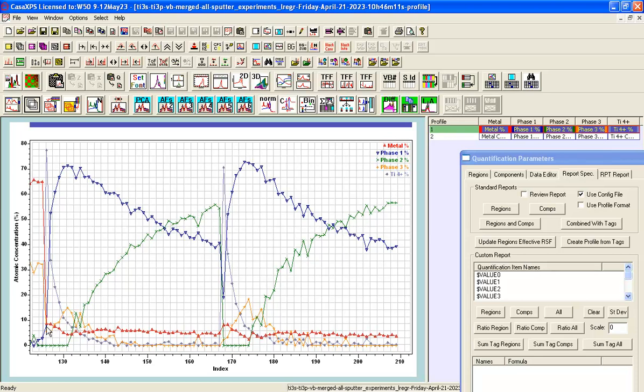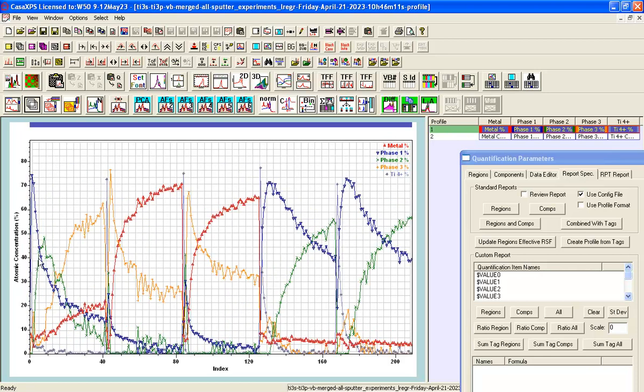And what's noteworthy is that throughout the entire measurement sputtering with helium, the metal signal remains constant. This has not changed over the course of the entire sputter cycles for helium. That's not the case for any of these argon sputtering where we can see the metal is progressing. So there's a different mechanism, but nevertheless the oxide is changed by whatever measurement we perform in terms of sputtering with an ion beam. Having data in this form gives me an opportunity to illustrate one of the display features